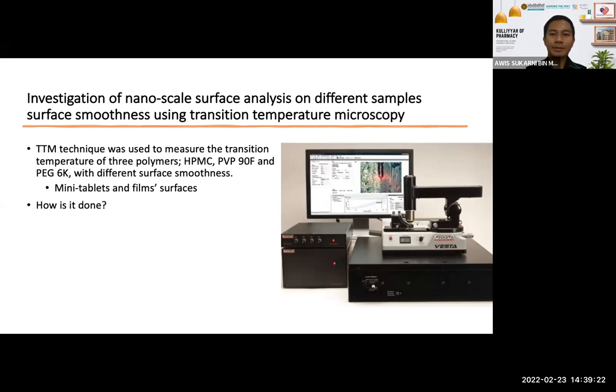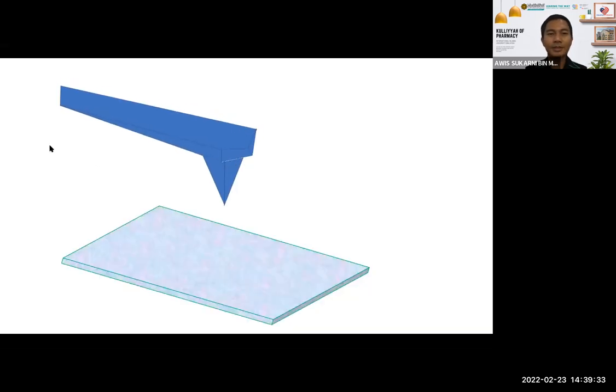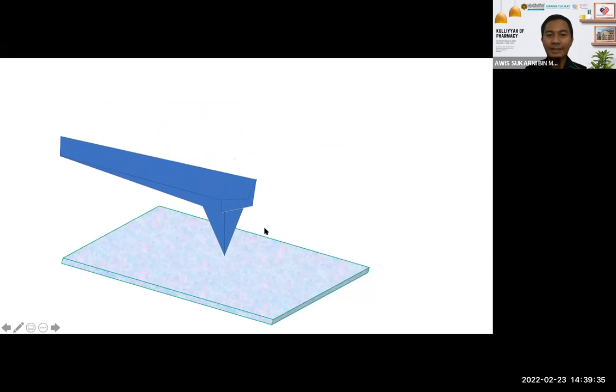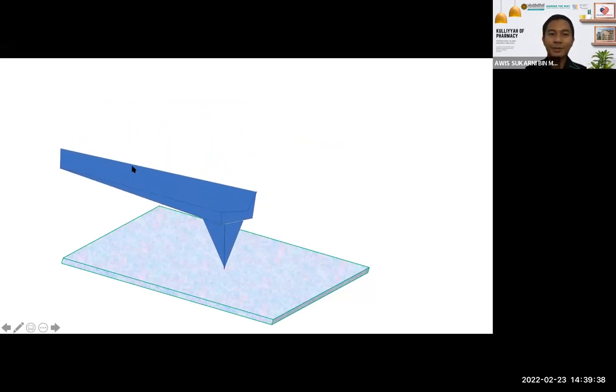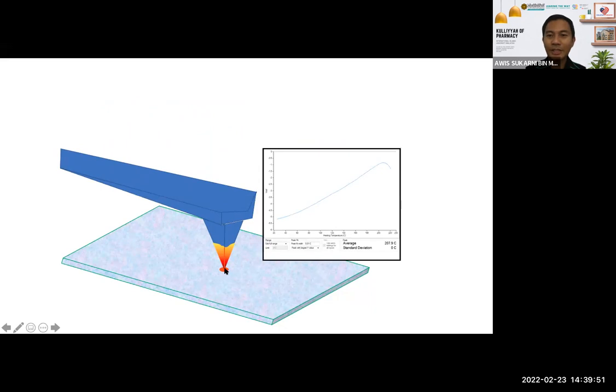And so before I go deeper into explaining about the study, I need to explain how this machine works. Here you can see there is the tip that is attached to the TTM. When you run the machine, the tip or the probe will lower down and touch the surface of the sample. At this point, it's going to heat up the sample, and then they will measure the transition temperature of this point here.